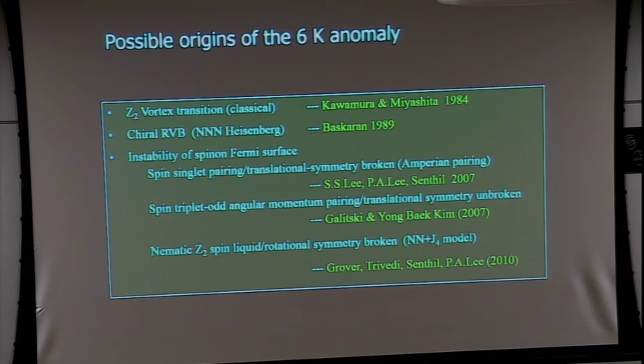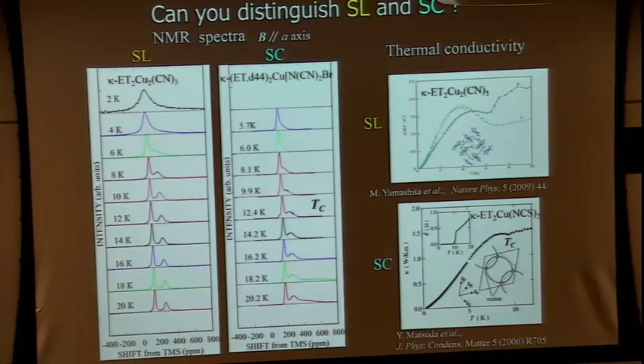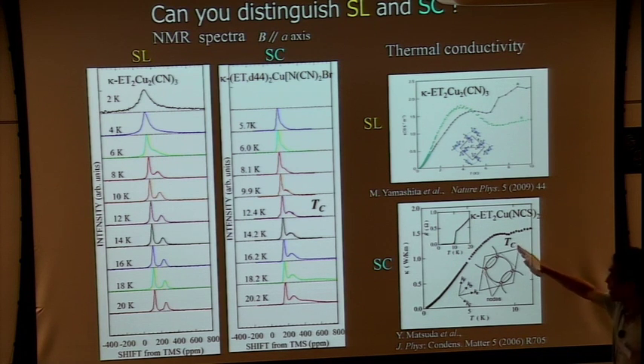Does that compare? I mean, what about the heat capacity of that? Yeah, that is a very difficult one, because at low temperatures, the phonon contribution dies, and then the electron contribution shows up. However, at high temperatures, maybe around 10 Kelvin, where Tc is 10 Kelvin, maybe 99% of the specific heat comes from the phononic part. So some anomaly occurs in superconductivity.